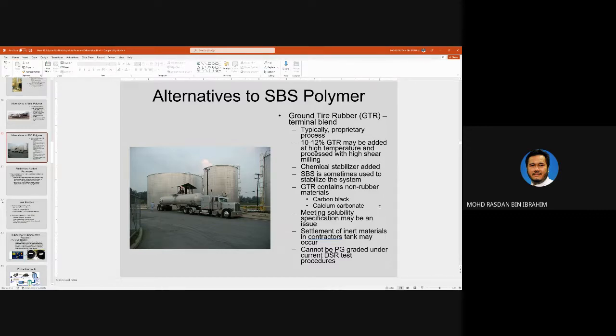It will never stabilize. So currently I'm conducting one research, where some of your friends are involved. We are doing the terminal blend, meaning that the rubber modified bitumen that we produce is going to be storage stable. There are other methods that people have used to stabilize the bitumen, but we are using a different approach. But the problem is the temperature is still very high. The rubber is mixed at more than 200 degrees. Typically, it is being mixed at around 160, 180 degrees. So the increase in temperature of blending is not desirable, because it consumes lots of energy.